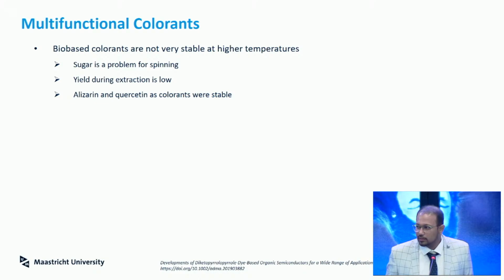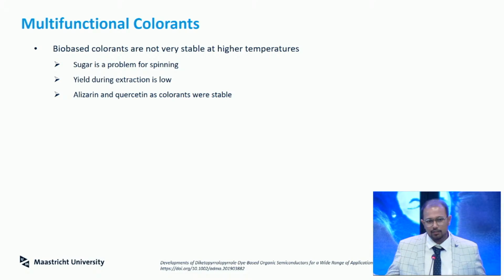What we noticed was that a lot of the times they were not really thermally stable. The sugar was a problem, and yield during the extraction was also quite low, which was notified to us by our partners. They could only get like 10% yield, whereas the fossil-based variants were actually quite stable. Even if it was the same molecule, instead of being extracted from natural sources, if it was made from oil, the molecule as such was stable.